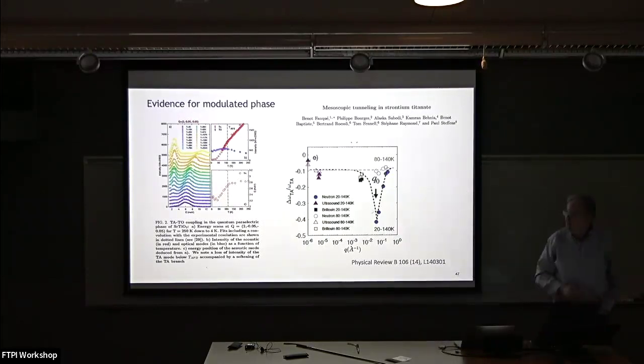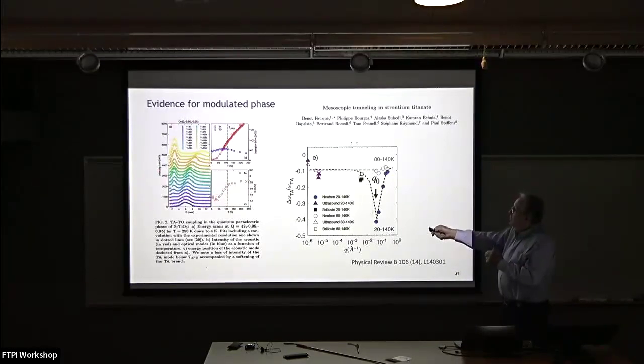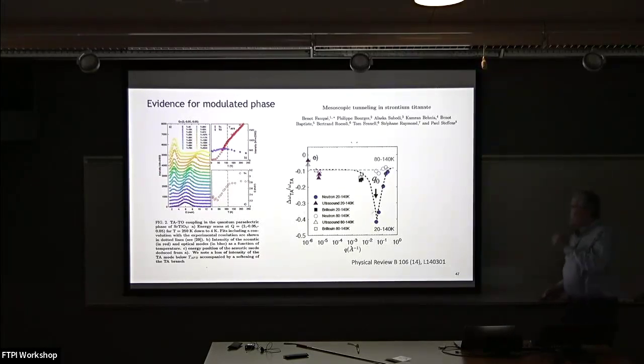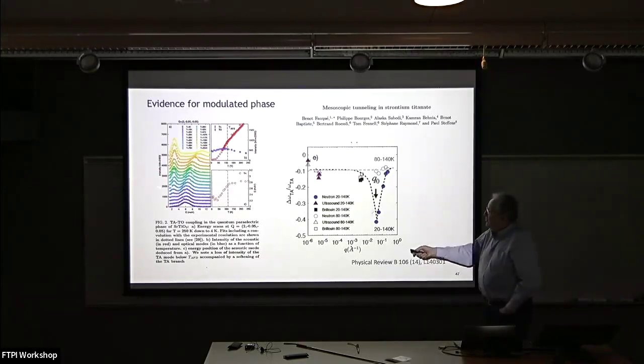So this is inelastic scattering energy in this direction. But you're sitting at a Q vector which is a little bit off the Bragg peak. And for that reason, you can actually see the acoustic mode as well as the optic. The thing you notice here is that the optic mode is softening, as we expected. That's the divergent dielectric. But then if you look carefully, you can see that it's actually pushing the acoustic. And somewhere down at the bottom, you can't see the acoustic.